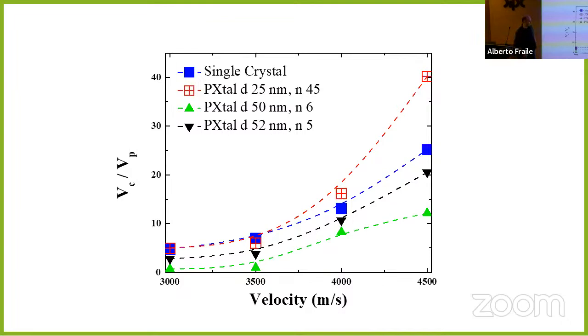Okay, so I hope you didn't find it boring. No, as I told you, in the beginning I did some experiments on beryllium and tungsten, on how this grows. The background behind it was always why we were doing that: they wanted to use it in fusion physics. I'm not sure anymore what the reason was to use beryllium, but it had certain properties that tungsten alone did not have. Beryllium was used in JET, in the tokamaks, this European facility in the UK. I think it's good because it's a low-Z material, so you don't want high-Z materials in the plasma. But it's very toxic, so it's really a mess to work in that environment.